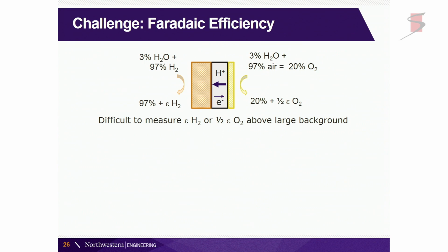And so it's also quite difficult to measure the Faradaic efficiency. You might think, well, just put a detector and measure how much hydrogen you're producing. That would be the obvious answer. The reason that it's difficult is that we're typically supplying this very high amount of hydrogen to see how much additional hydrogen we could make, and as I said, pump up some sort of tank so that we could have high-pressure hydrogen. So now if you're producing a small amount of hydrogen from this 3% steam, that's hard to detect over a large background signal.